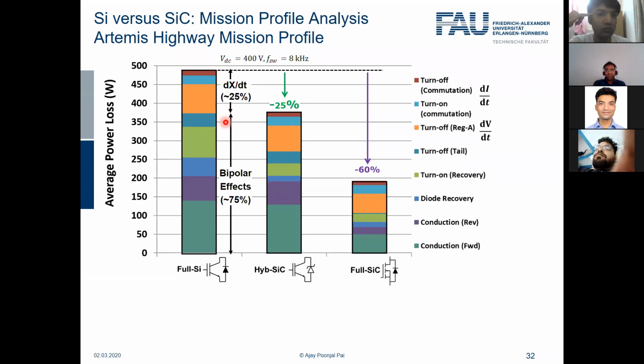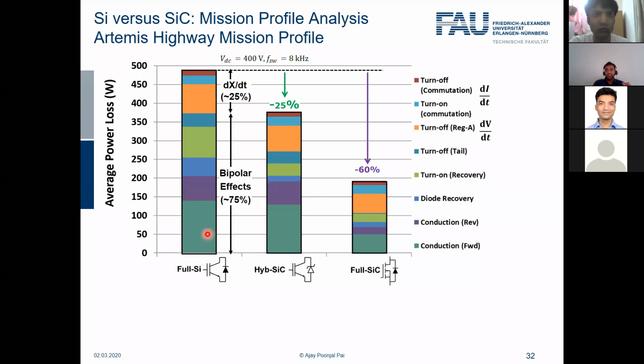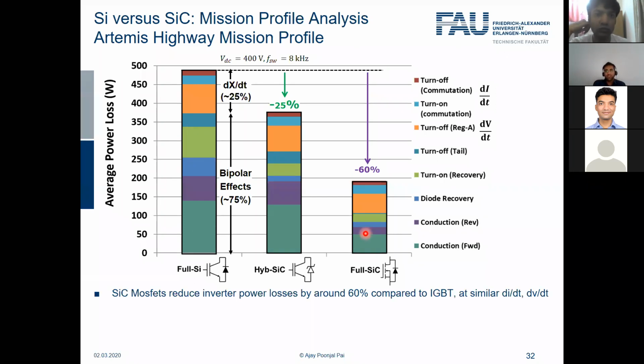So if you see here once again, 75% of the total losses are coming mainly because of bipolar effects, like tail current, like recovery, and so on. And only 25% of the losses are coming because of switching faster or slower. So even if you switch the IGBT really fast, you can influence mainly only this 25%. The others will remain more or less the same. Of course, when you switch faster, the reverse recovery will actually increase, but you can influence mainly this 25%. So even if you switch an IGBT very fast, you will not be able to influence this big 75%. And for that, we need to go from a bipolar device to a unipolar device. So this is the message.